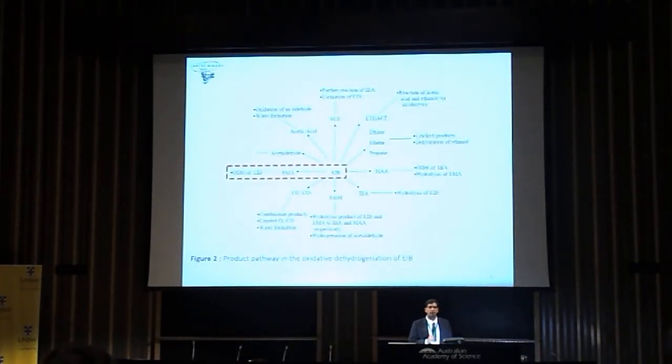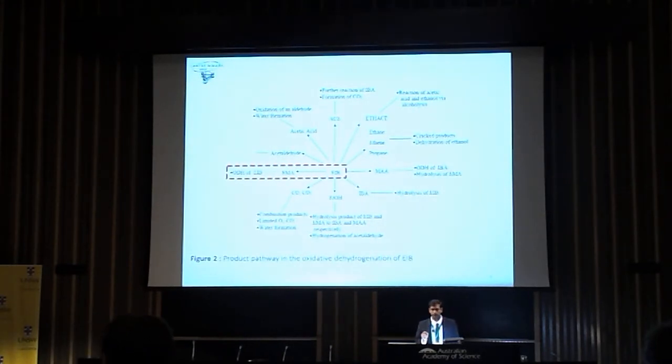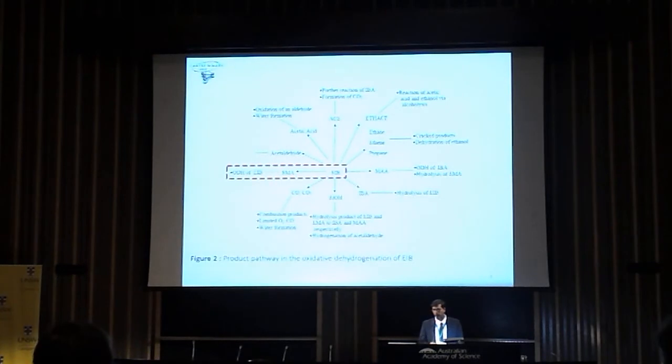But one of the major drawbacks of these gas phase oxidation reactions is that instead of the reaction going only towards our target product, several reaction pathways go on at the same time. The red block shows the ODH of EIB to EMA, but at the same time unwanted products like carbon oxides, acetaldehyde, and cracking products like ethane, methane and propane were forming.